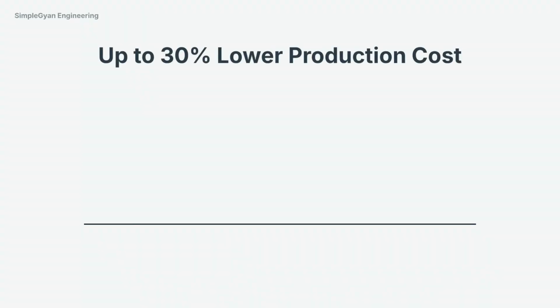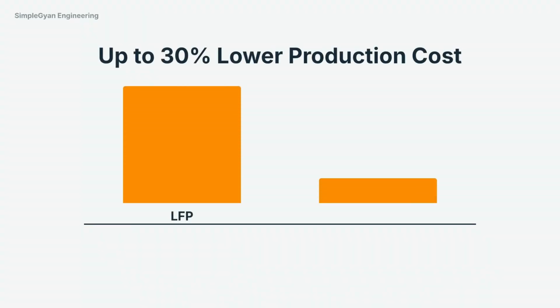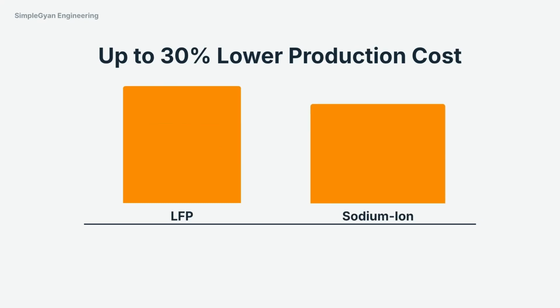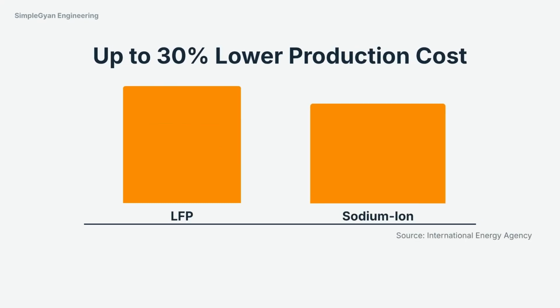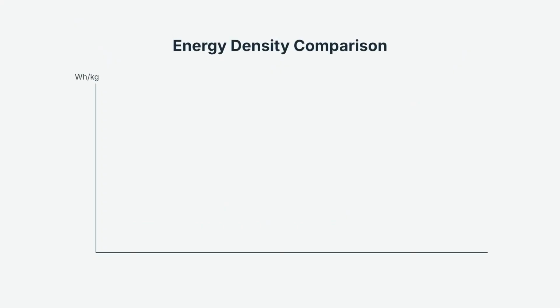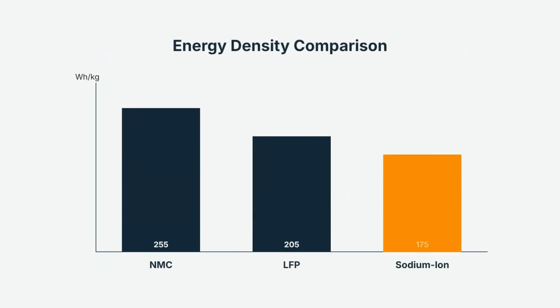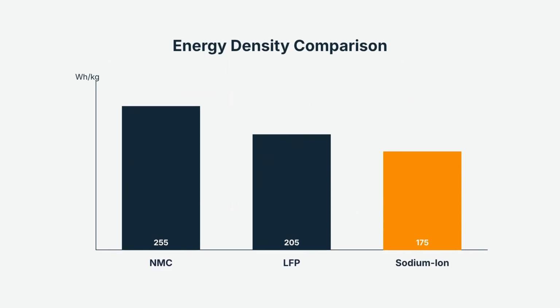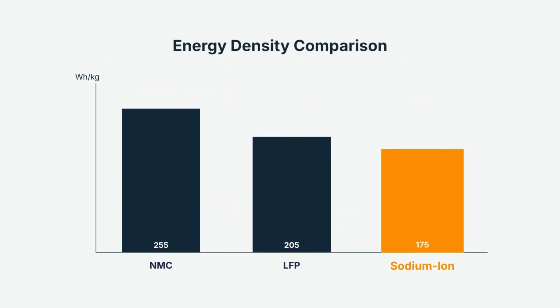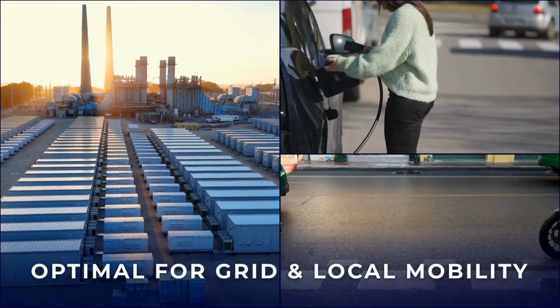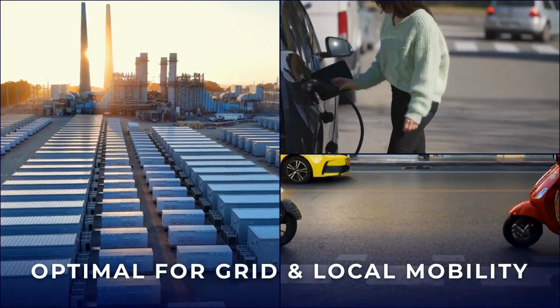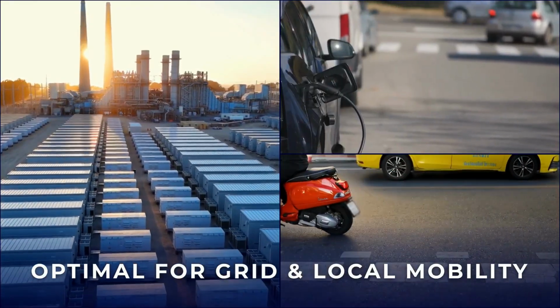The International Energy Agency reports that sodium-ion batteries may have production costs up to 30% lower than LFP batteries in some scenarios. But it's not a magic replacement. Its biggest weakness is lower energy density, around 175 watt-hours per kilogram compared to 255 for NMC lithium-ion. So while they may not dominate luxury EVs, they are extremely important for grid storage, two-wheelers, and cold climate vehicles.